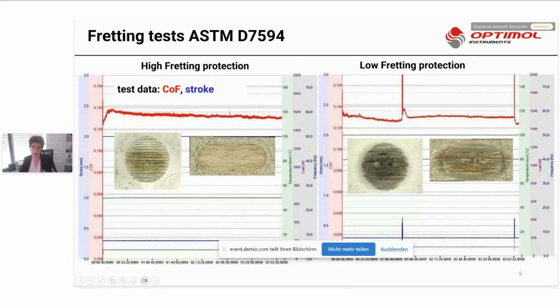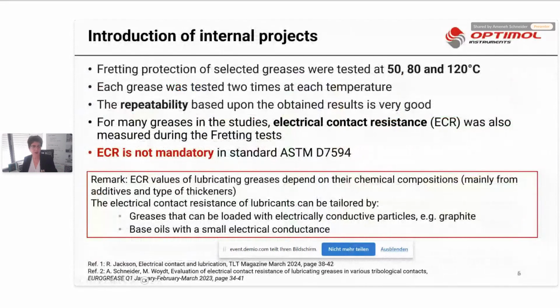And having a look under microscope to check the wear scar on the ball and on the disc, you see in the case that you have a very high fretting protection system, or let's say greases, you have a very nice protection here. For a low fretting protection system, or let's say your coating or your alloy or your grease is not a good fretting, has not a good fretting protection. After a short time, you have an adhesive seizure here. You can see it very nicely also under microscope, lot of pitting here, and it reflects also directly in the fluctuation of your frequency during the test. Actually, very, very obvious, working very nicely, this standard method.